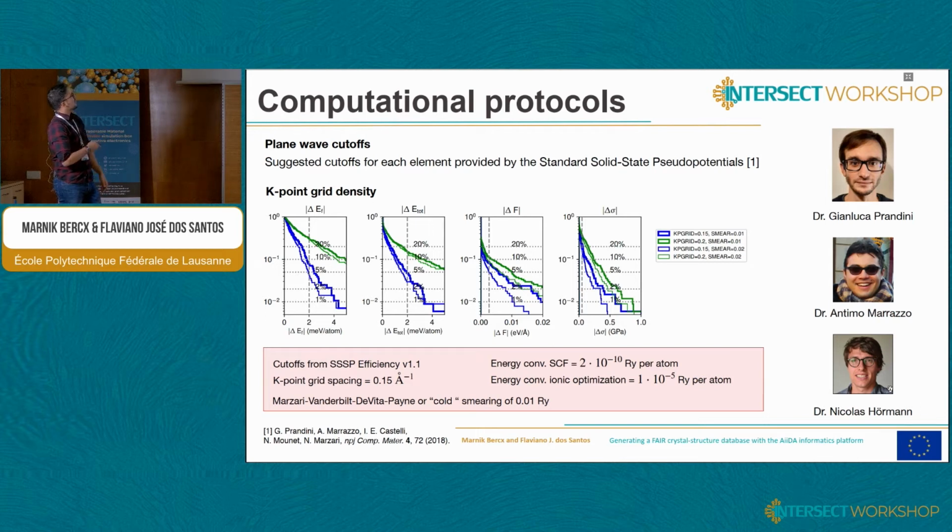For the other computational parameters, we're also relying on a former colleague, Nicola, and his work. He basically took, in Quantum Espresso, a very strict set of convergence parameters, and then for a set of diverse structures, slightly relaxed each of these step by step to figure out: if I compare, for example, the total energy to this very strict set of convergence parameters, what is the error I get compared to that? And so here we can see for this sort of K-point grid and smearing, for 95% of structures, we still have a precision within 2 milli-electron volt per atom.